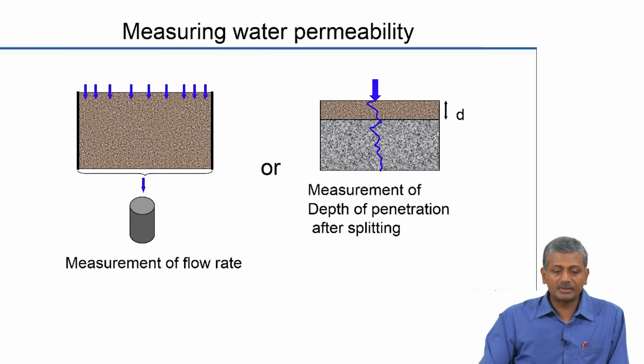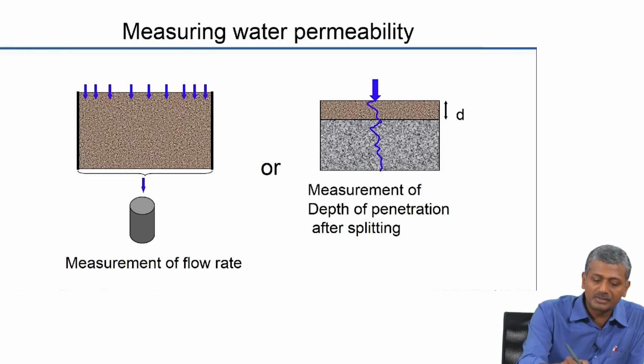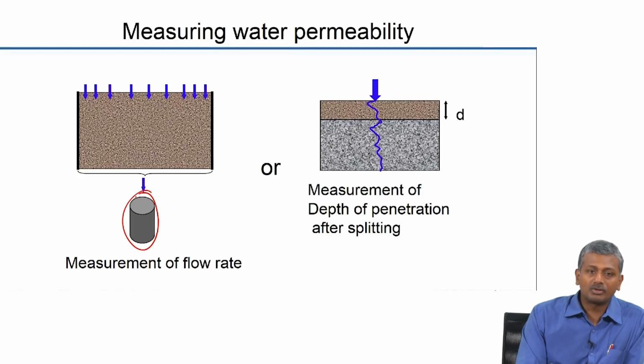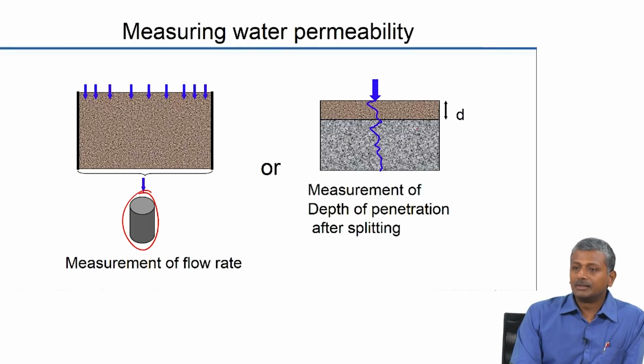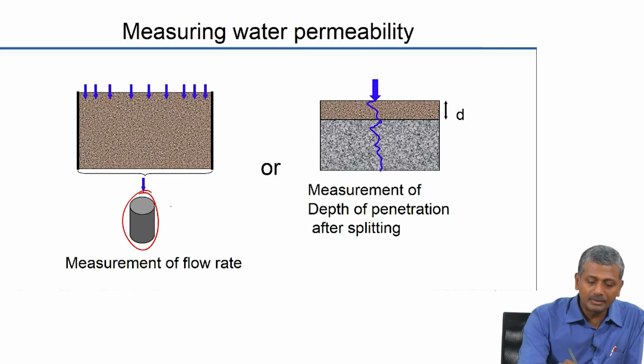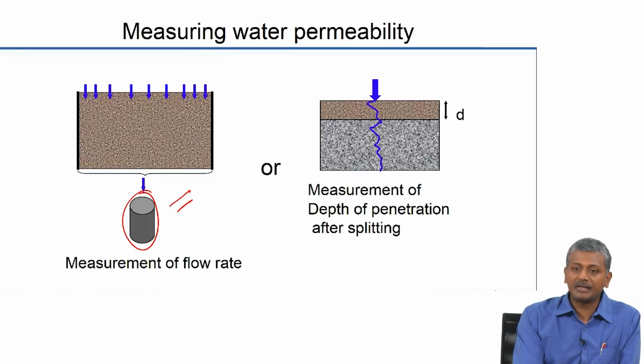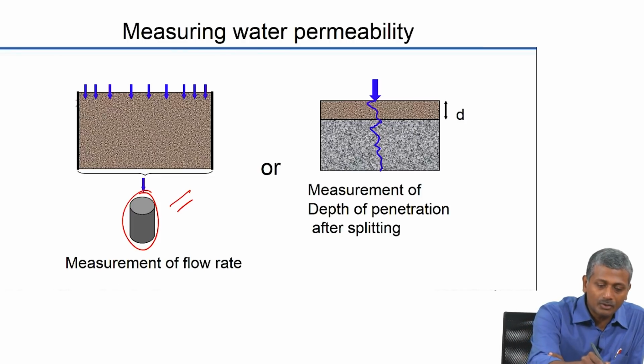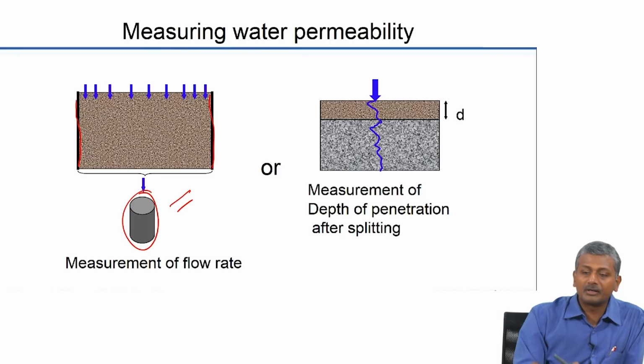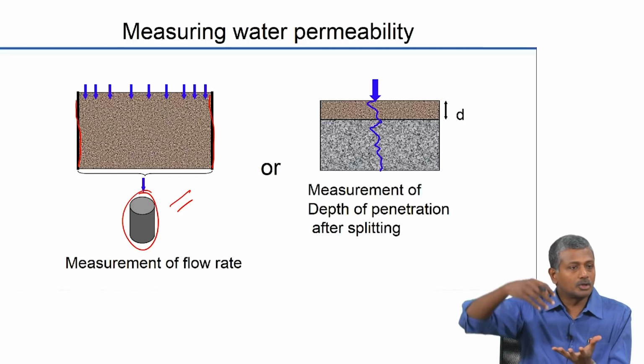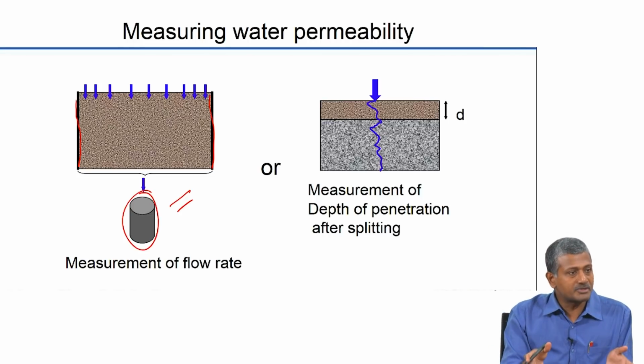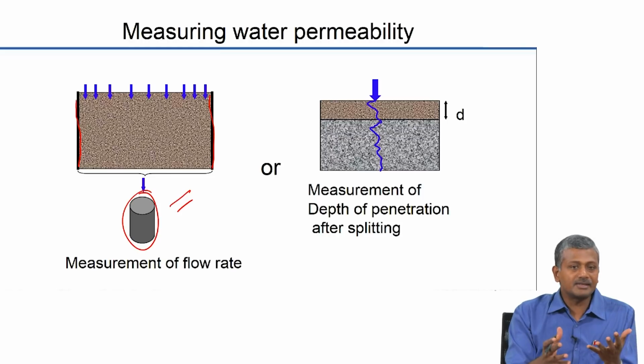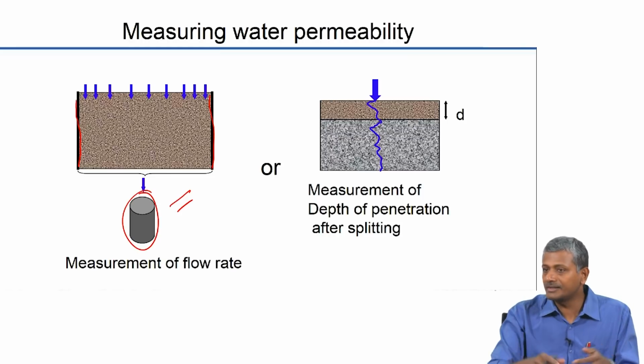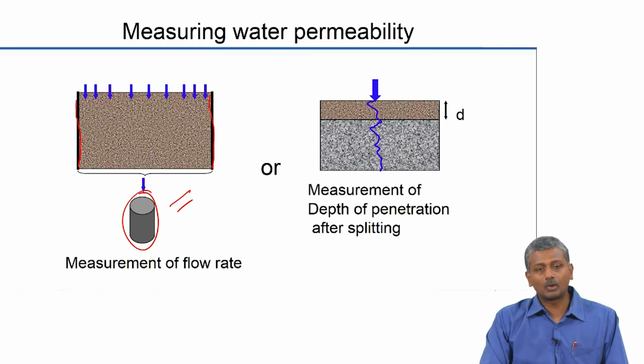Okay? So these are two different methodologies. One is obviously looking at the flow rate of water flowing out through the concrete. The other is the depth of penetration of water after a certain amount of time. Now, the other disadvantage with the water permeability test is that sealing the sides of the concrete can be a really difficult task, because you want the water to actually flow through the concrete and not from the sides. So sealing the sides and ascertaining that water does not flow on the sides takes a very long time to set up.